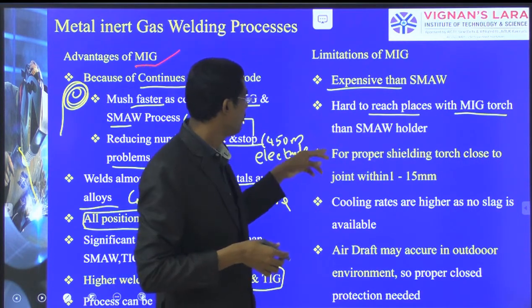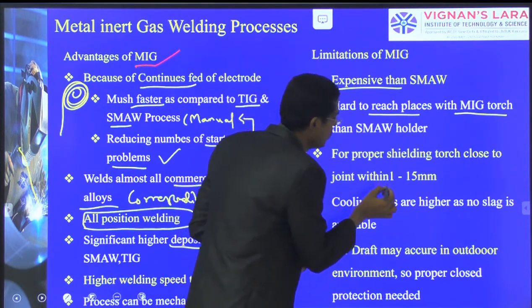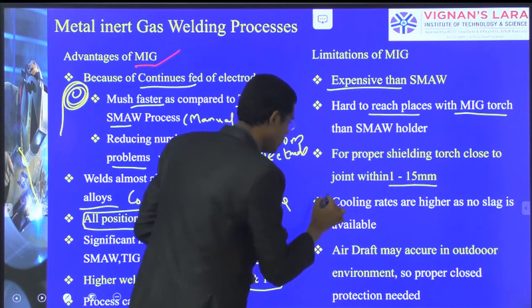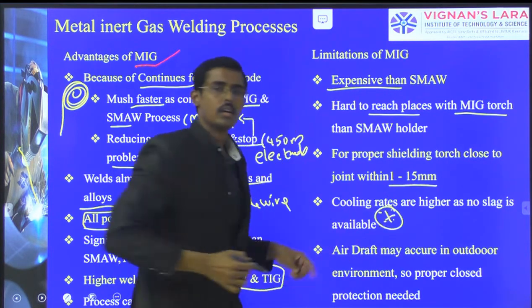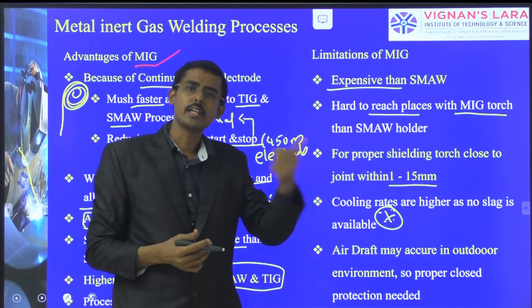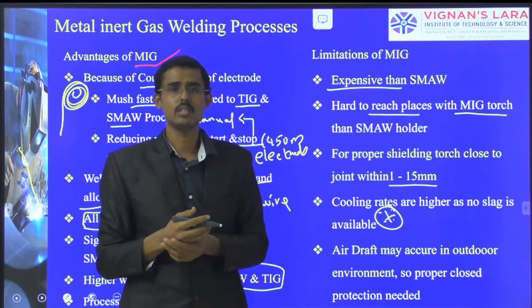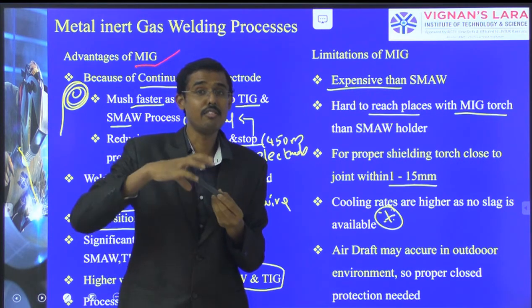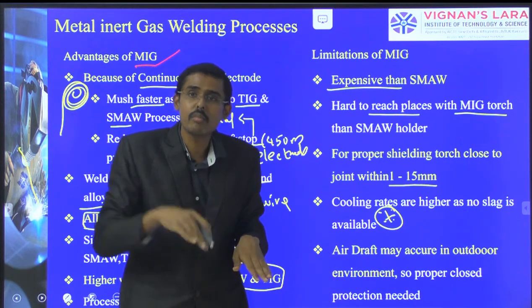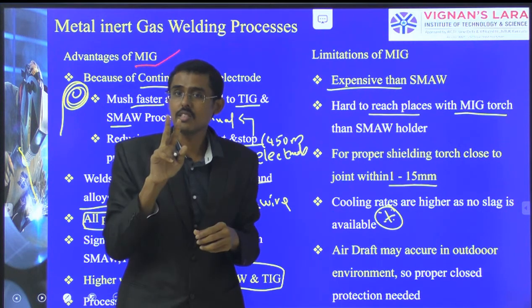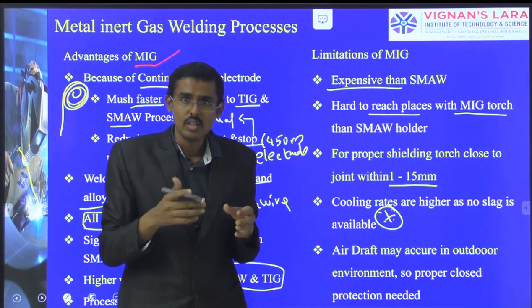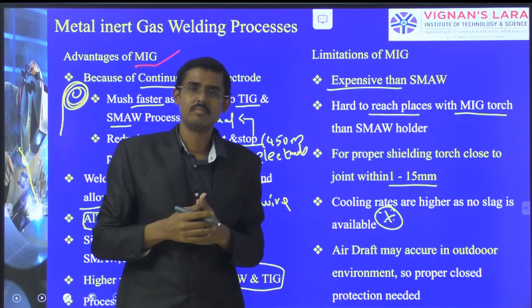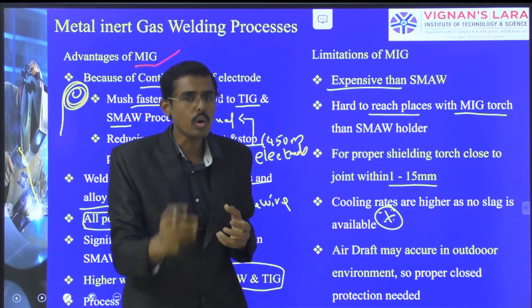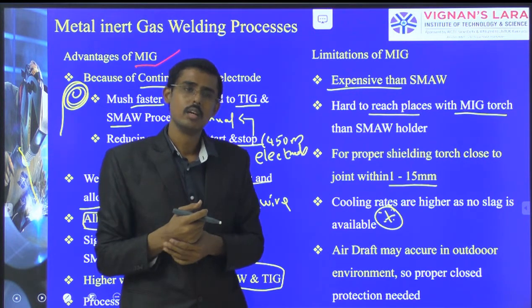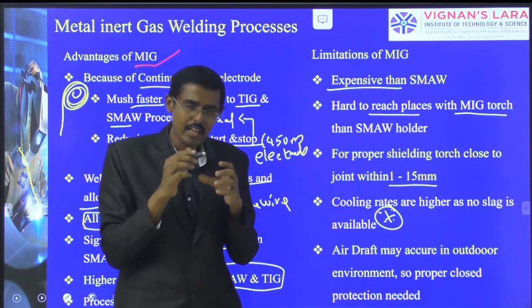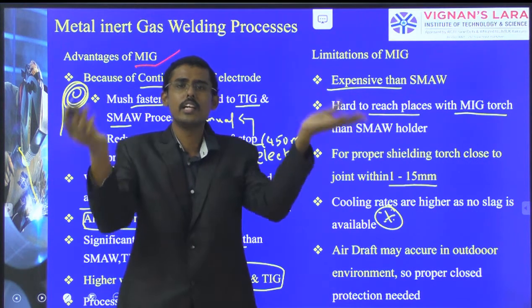That difficulty is there. For proper shielding, the torch must be close to the joint, within 1 to 15 mm, and cooling rates are higher. Very important point. In shielded metal arc welding or submerged arc welding, we use external fluxes, which act as a protective layer from atmospheric contamination. That is one advantage. Second, it protects against fast cooling. It keeps the weld metal warmer, cools it slowly, and acts as an annealing treatment also. But here there is no flux. Whenever welding is completed, the weld is directly exposed to the environment.